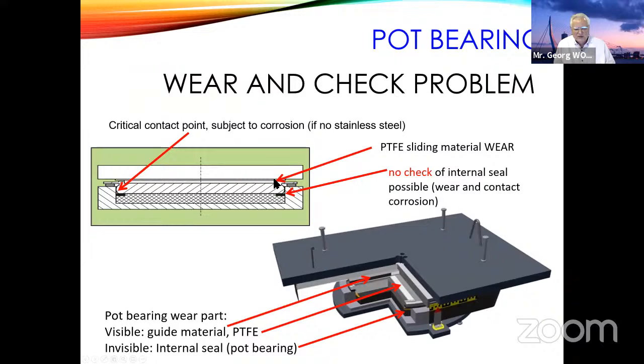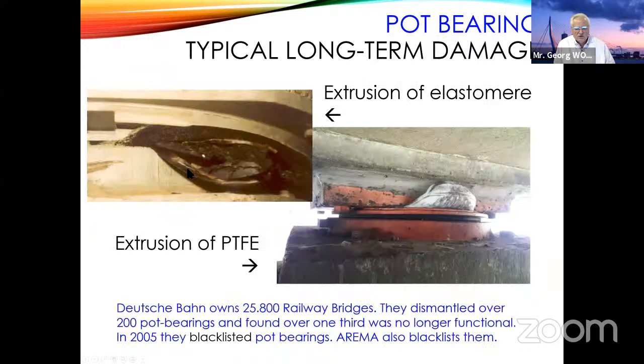Yes, the PTFE you can check from outside, but the pot itself inside you cannot check. And this is how the damages look when the rubber is extruding because the seal is failing, or when the PTFE is extruding. The Deutsche Bahn was the first one who found out a lot of damages. They own 25,800 railway bridges and dismantled over 200 pot bearings. They lifted the bridge, took out the bearing, opened it, and then they found out one third was no longer functional. The age of the bearings was between 20 and 40 years, something like that. The process went until the end of the 1990s.